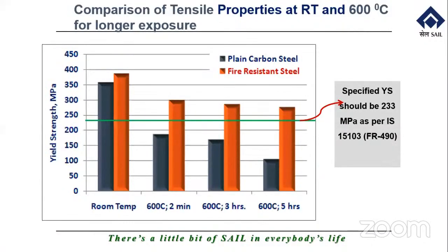dimensions. So if we talk about exposure, then the comparison between plain carbon steel and fire resistant steel is very much explanatory in the form of this graph here. Fire resistant steel gives yield strength much higher than our normal plain carbon steel, and it can withstand 600 degrees centigrade for up to 5 hours.